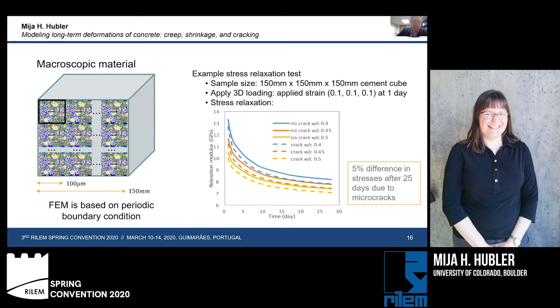Since our cement structures, concrete structures, are usually not 100 micrometers, we can now create a macroscopic material by taking this finite element model and assuming periodic boundary conditions. And now if we conduct our stress relaxation test on a 150 millimeter sample, we can apply a unit strain at one day. We see that our relaxation modulus over time evolves, and that in fact, we have a 5% difference in stresses after 25 days due to the appearance of microcracks.